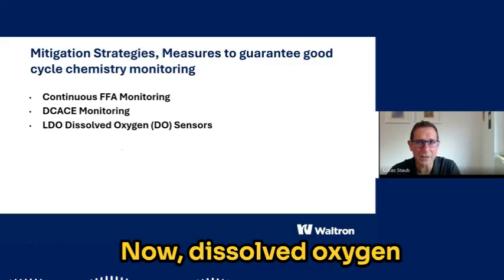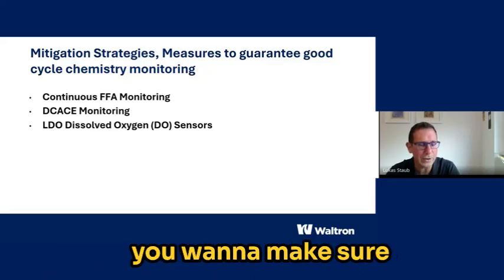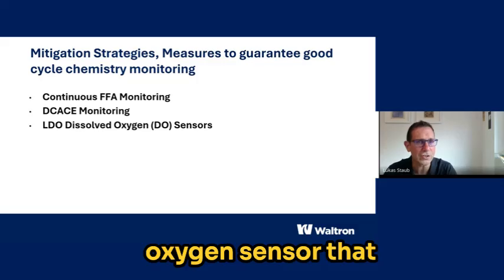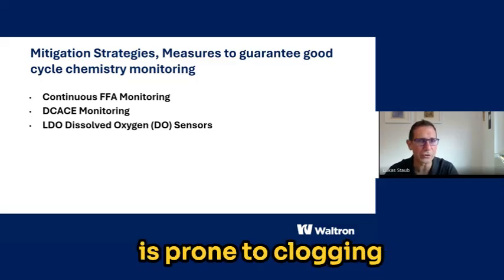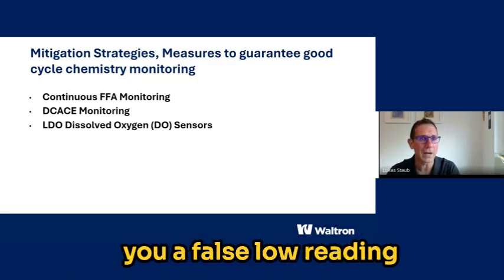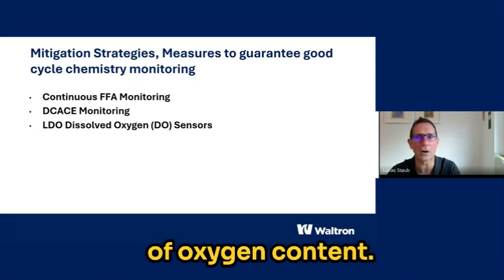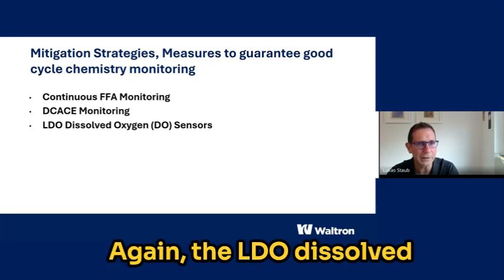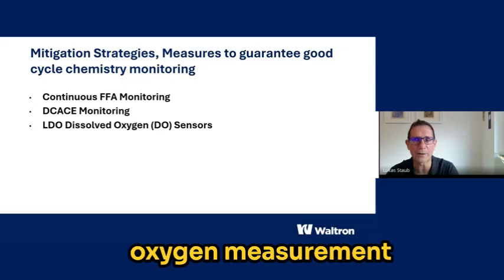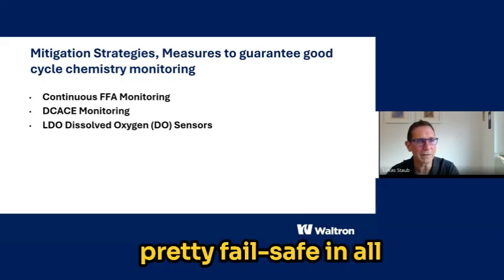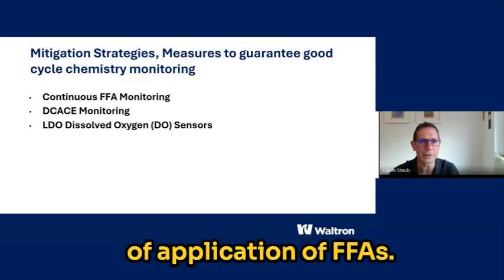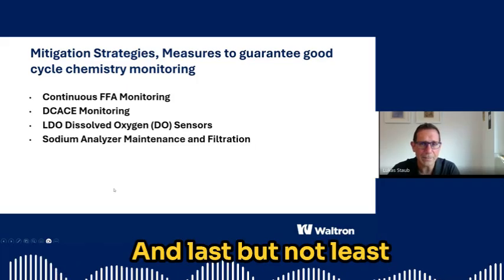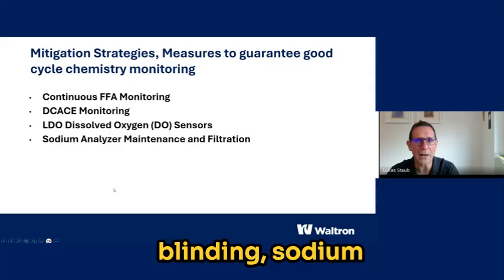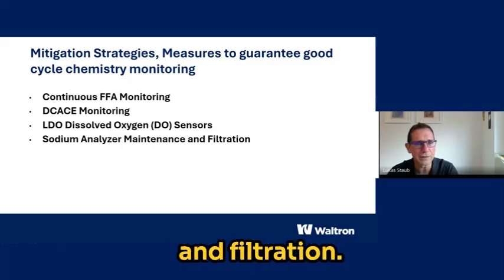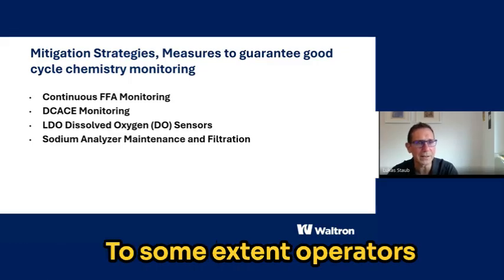Now, dissolved oxygen monitoring, of course, you want to make sure that you don't have an oxygen sensor that has a membrane that is prone to clogging, because this will give you a false low reading of oxygen content. Again, the LDO dissolved oxygen measurement has been proven to be pretty fail-safe in all kinds of application environments of FFAs. And last but not least, to avoid sodium blinding, sodium analyzer maintenance and filtration, to some extent, operators